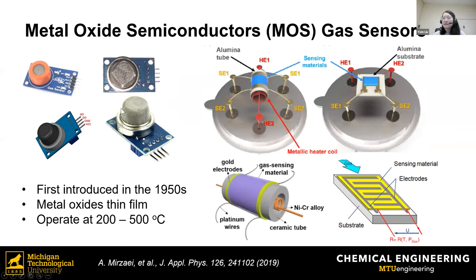Inside of this housing, there are usually two typical sensor designs. Either it's based on a ceramic tube, and inside of the tube we have the heater, and outside of the tube we have two electrodes, and between them is a sensing film, usually a metal oxide film. More recently, it shifted to interdigital electrodes, where the electrodes have those fingers. It's still a two-electrode system, but the two fingers have small spacing, so the material can better contact the electrodes, and the heater is on the bottom of the substrate plate. So these are the two typical sensor designs for semiconductors.